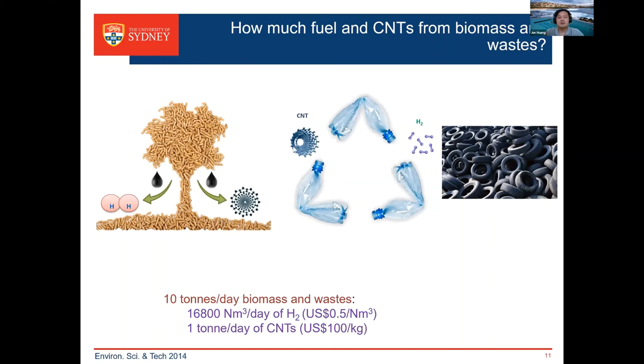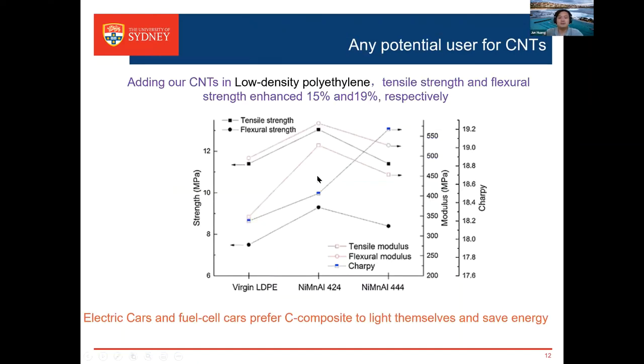And the quality of carbon nanotube is very good. We cooperate with a carbon composite company, using a mixture of our carbon nanotube in polyethylene. So we are able to increase the strength by around 15 to 19% for this kind of material, as a commercial carbon nanotube can do.